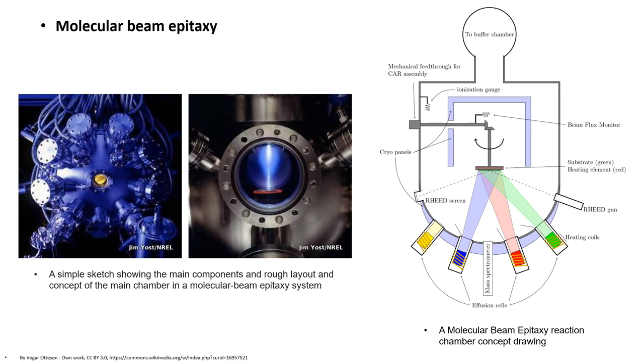In solid source MBE, elements such as gallium and arsenic in ultra-pure form are heated in separate effusion cells until they begin to slowly sublime. The gaseous elements then condense on the wafer where they may react with each other. In the example of gallium and arsenic, single crystal gallium arsenide is formed. The gaseous elements impinging on the surface may be adsorbed after a time window where the impinging atoms will hop around the surface or reflect off it. Atoms on the surface may also desorb.